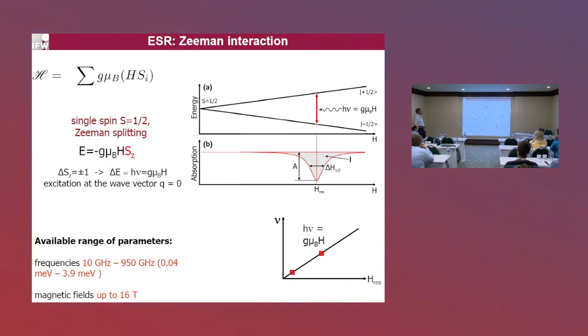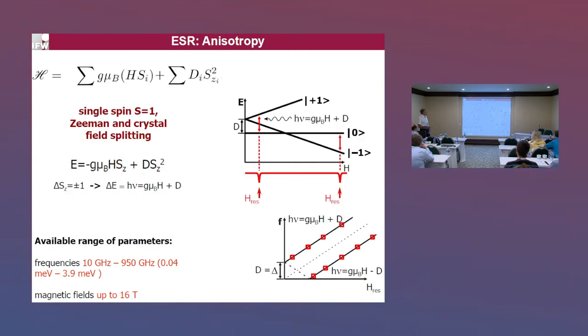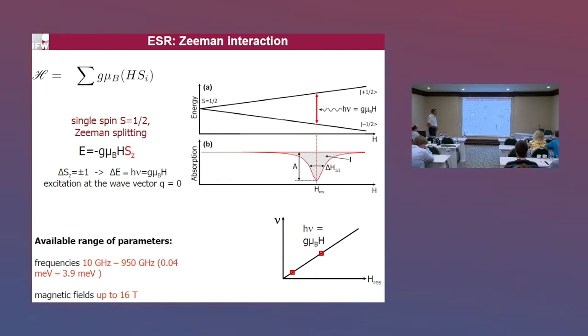The principle of electron spin resonance spectroscopy is very simple. For a spin-1/2 particle, in zero field the two possible energy states — spin +1/2 and −1/2 — are degenerate. One applies an external magnetic field and splits these two states according to the Zeeman effect. If one shines electromagnetic radiation of appropriate energy matching the gap between the split states, the electron spin system will absorb the energy, giving rise to a resonance signal. Changing the excitation frequency changes the resonance field correspondingly, and plotting frequency versus resonance field yields a straight line from the origin.